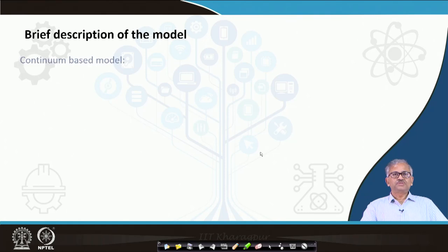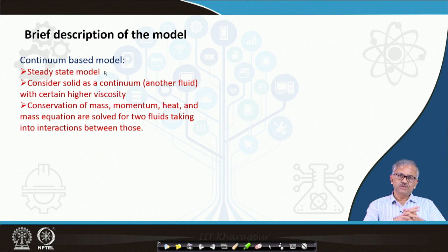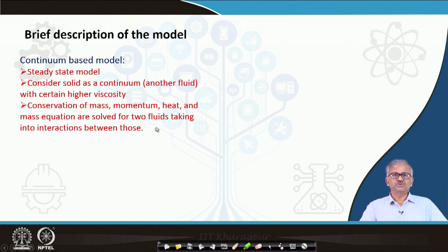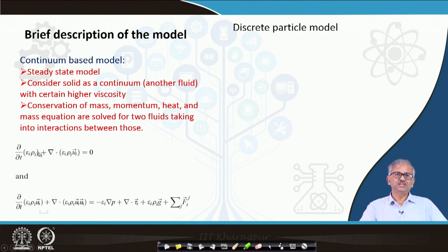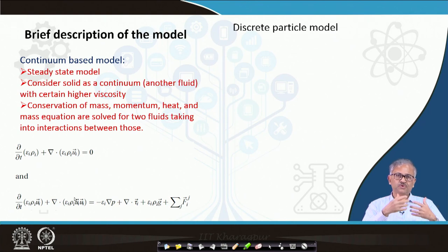A brief description of the models: the continuum-based model that exists for the blast furnace is a steady-state model. It considers solids as a continuum — another fluid with certain higher viscosity. Conservation of mass, momentum, heat, and species equations are solved in two fluids taking into account interaction between them. This is the continuity equation and the momentum equation with three components, plus enthalpy balance and species balance equations. If you want to solve in turbulent flow, a turbulence model like k-ε will also be there.